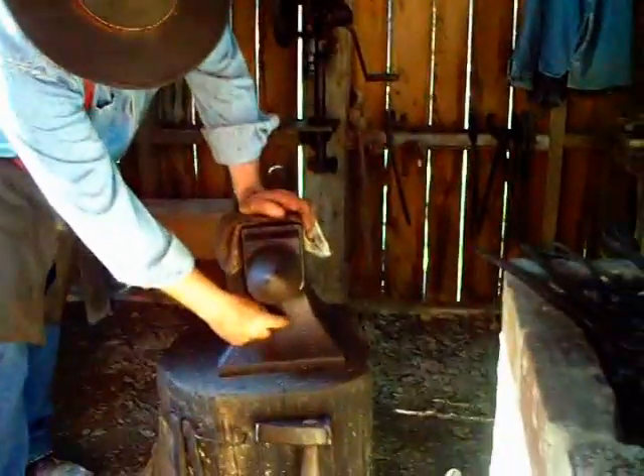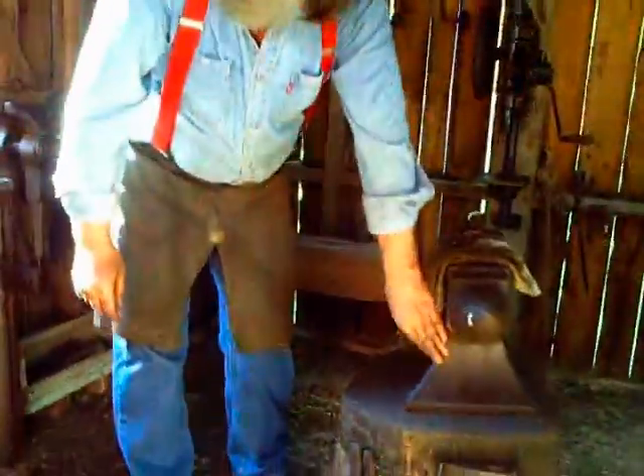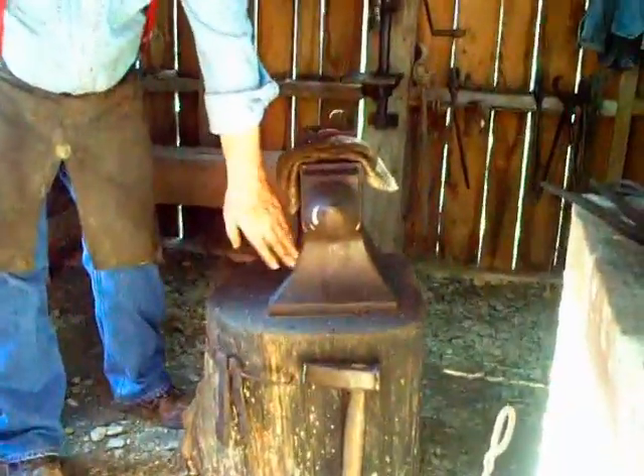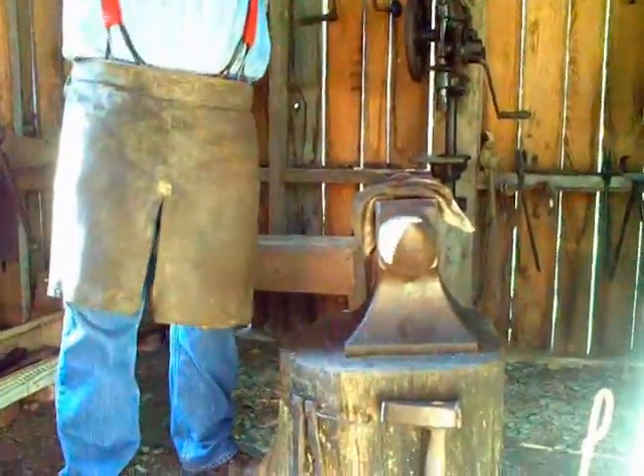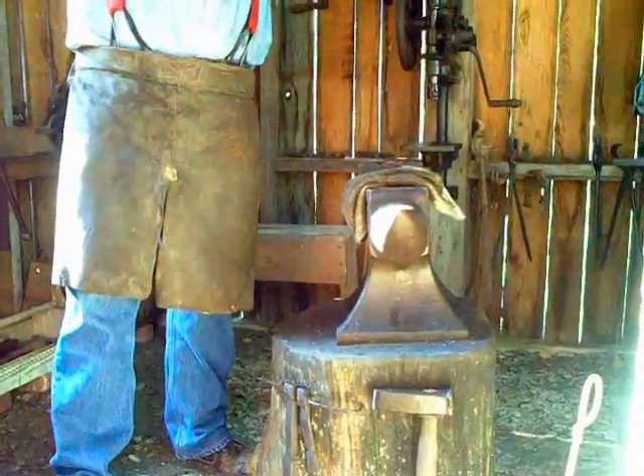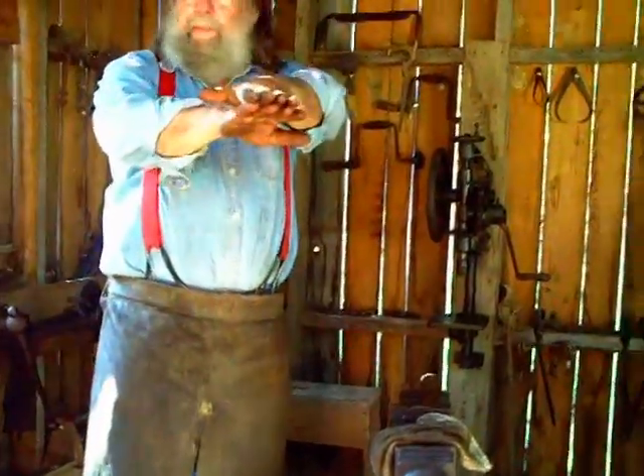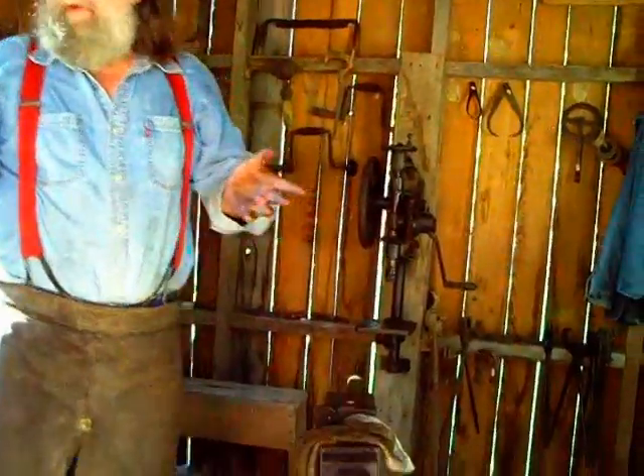All right. One thing I failed to mention: if you ever look at an old anvil and there's a square down here on each side, this is probably a wrought iron body. Those are tong holes, because whenever they welded a steel face on them, the anvil is actually upside down. They put the steel into one forge, the anvil into another forge, and bring them up to welding temperature, set them down, put them together, roll them over, and set the weld with a hammer.